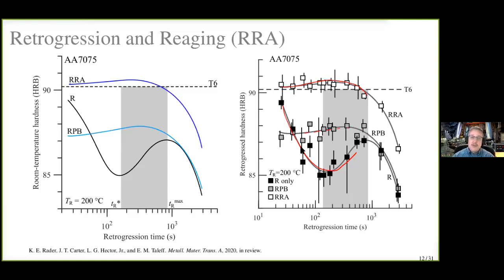So our idea is while we're retrogressing the material going along this curve, we're going to use that warm temperature, increased ductility, reduced flow stress to form a part. After the part's formed, we're going to apply that single reaging heat treatment and get the strength back up to here. And that's kind of the process that BMW is trying, you probably should have used for that component they were making. Now, we have to watch out for something here. You notice that at this TR max value here, once we reduce strength past that time, our recovered strength after reaging is less than T6.